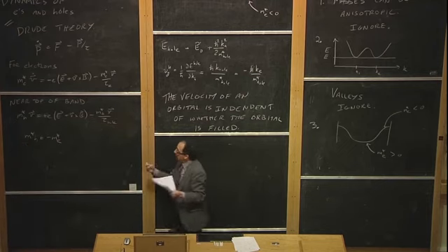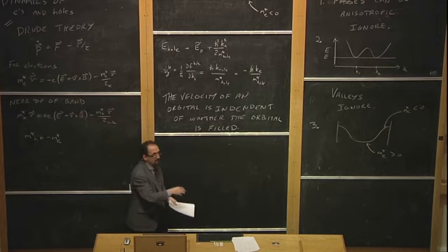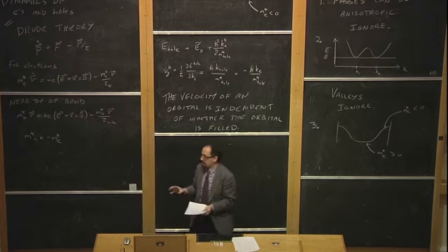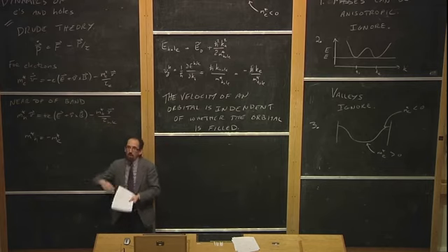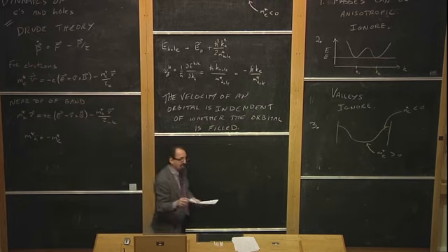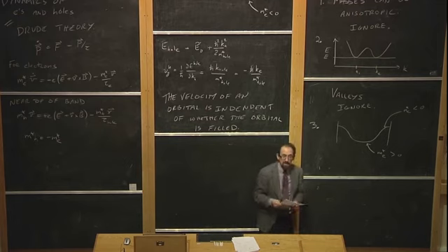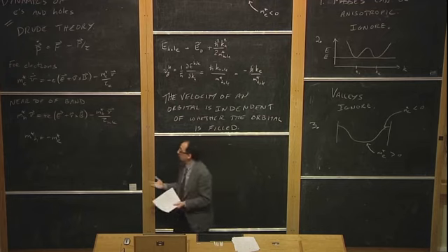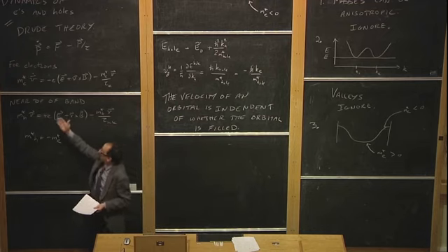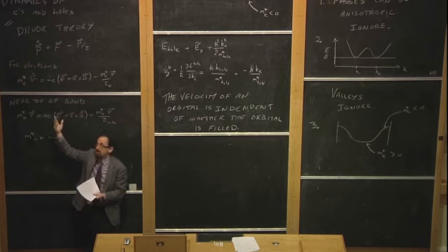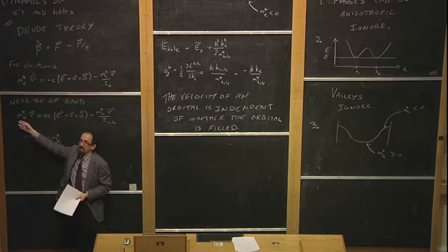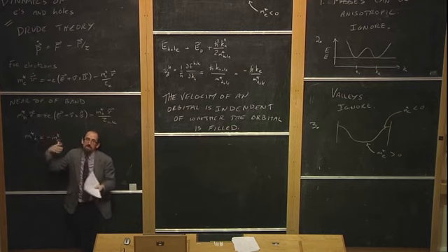So this is actually quite important. It's exactly the same statement that I just wrote over here. The dynamics of the state are exactly the same whether you're talking about an electron moving in the state or a hole moving in the state, the absence of an electron. The orbital still moves with the same dynamics whether or not the orbital is filled with an electron. Okay? Good? So the thing that's funny about the Drude equation in these semiconductors is that if you're up at the top of the band, you have a choice of two things that both seem a little bit weird. One possibility is that you have to think about a negative mass for the electrons if you're thinking about electrons in the state. The other possibility is you think about positive mass holes, but now these are positively charged particles.